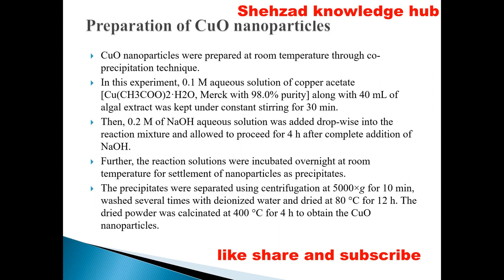The precipitates were separated using centrifugation at 5000 × g for 10 minutes, washed several times with deionized water and dried at 80 degrees centigrade for 12 hours. The dried powder was calcinated at 400 degrees centigrade for 4 hours to obtain the copper oxide nanoparticles.